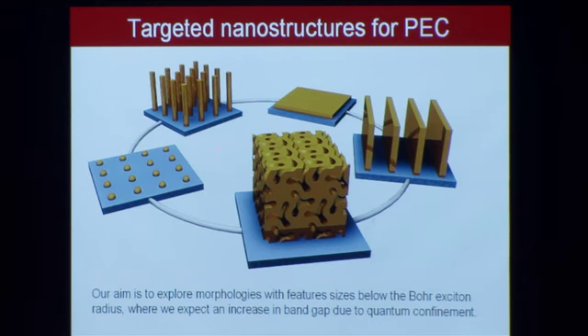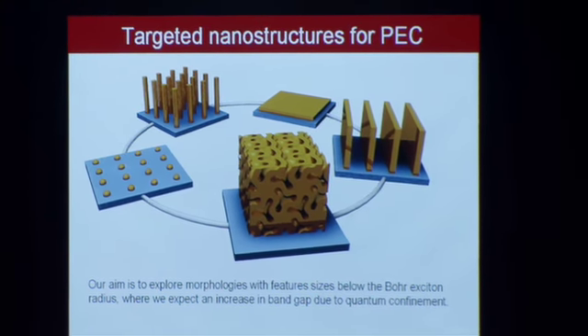And so we'd ultimately like to, say, grow nanowires that are of that dimensionality. They're quantum confined in the XY plane, but not in the Z plane. And that way you can orthogonalize the light absorption path length with the quantum confinement effect. So nanowires might be more useful, planar structures, vertical planar structures, mesoporous materials. As long as the feature size is below that Bohr-exciton radius, which in the case of moly sulfide or tungsten sulfide turns out to be 12 nanometers, we should see this effect. So that's our working hypothesis.